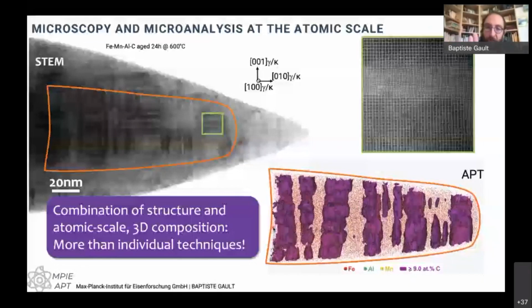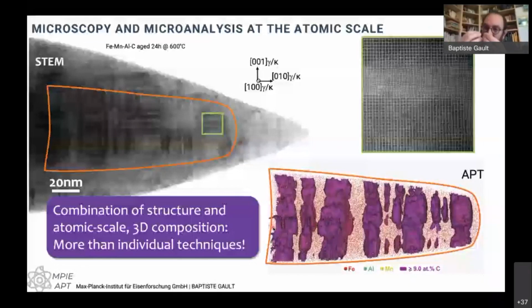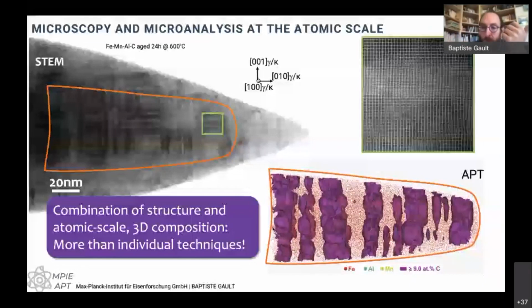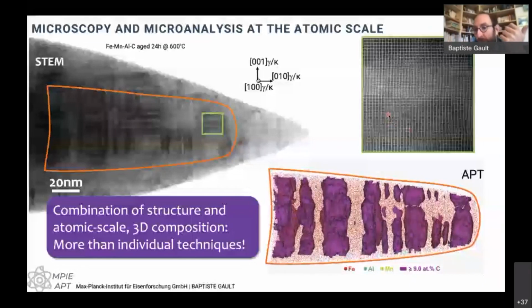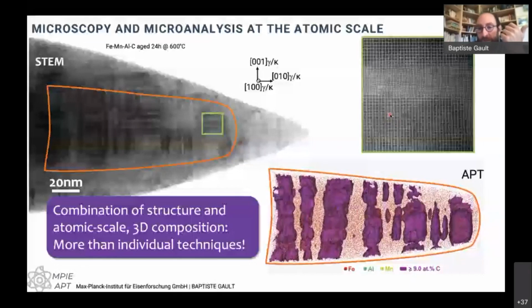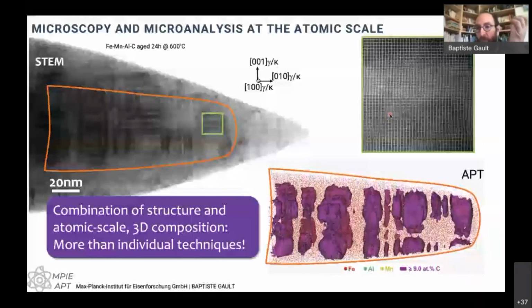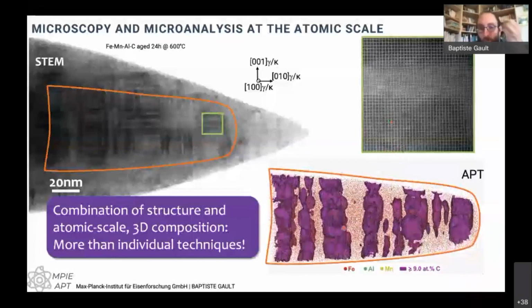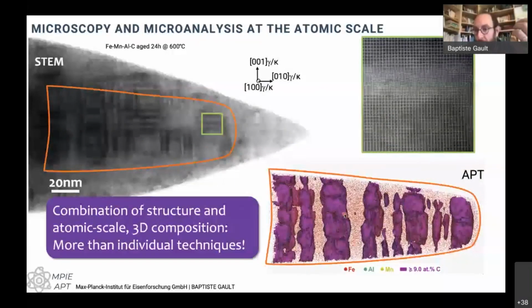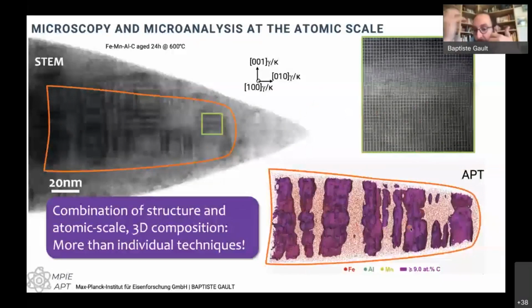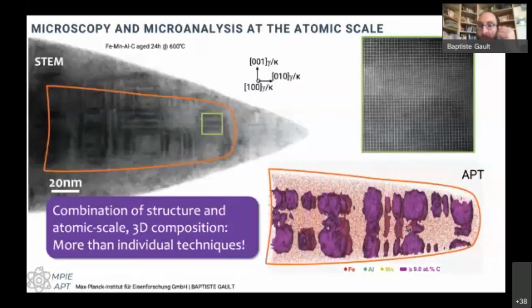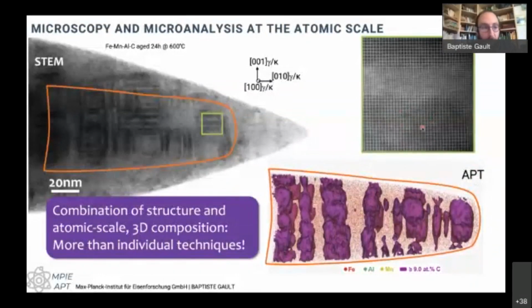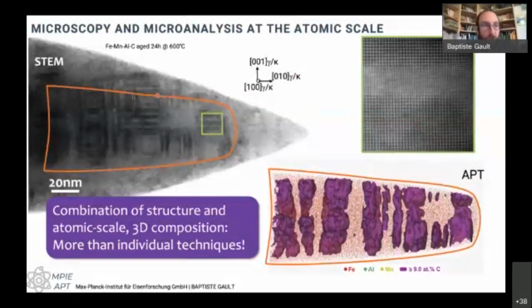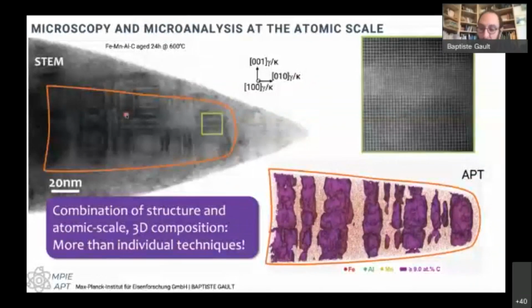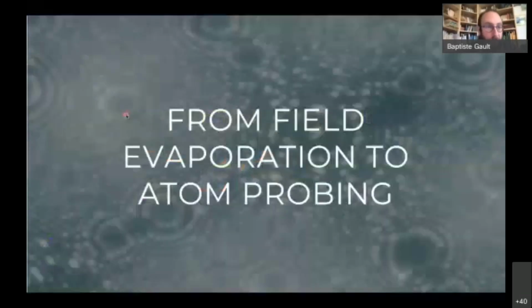which can sometimes have very similar Z numbers, so very close atomic weights if you want. So if I look at one of these columns, I can't really tell you whether the dark bit here is iron or manganese because they more or less have the same weight. But from the atom probe, I can tell you that within one of those precipitates, I know exactly how much of each of the species there can be. So these particles, these precipitates are actually carbides. So they will contain quite a lot of carbon, which is also a major challenge to measure by electron microscopy techniques. So how does an atom probe work?